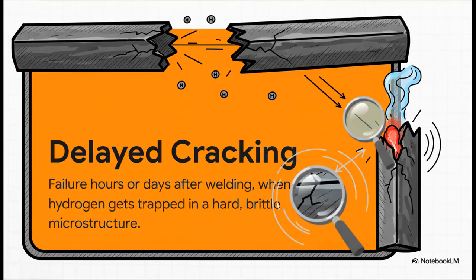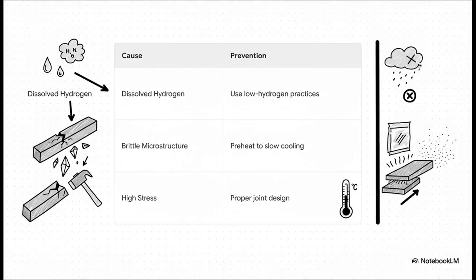One of the sneakiest ways a weld can fail is through something called delayed cracking. This is when tiny hydrogen atoms, maybe from moisture in the air or on the steel, get dissolved into the molten weld. If that weld then cools too quickly and forms that hard, brittle martensite we just talked about, the hydrogen gets trapped inside. Then, over hours or even days, that trapped hydrogen builds up immense internal pressure until it literally cracks the weld from the inside out. So how do you prevent that? Well, you have to attack it from a few different angles.